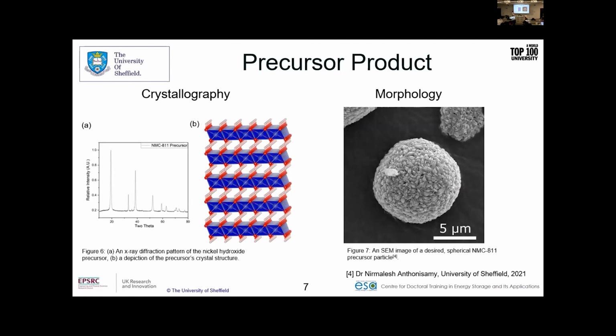But from a crystallographic point of view, we're looking for this nice layered structure here. So this is the precursor. You can see there's no green lithium in here. Instead, we've got these nice hydroxide ions here, so you've got the red oxygen and the white hydrogen. What that does is provide a larger interplanar gallery, so it allows lithium to go in when we grind it and calcine it, so that there's more space for the lithium ions to intercalate during synthesis.